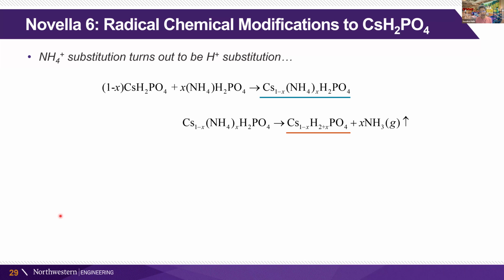What we discovered was that when we heated this material up to try to do the conductivity measurements and the thermal analysis, the ammonia, the NH3, evolved from the compound, and we were left with a material that was cesium deficient, and effectively proton doped. Now, we would have never tried to substitute cesium ions with protons because the size difference is so immense. Yet that's effectively what we created when we attempted to do ammonium ion doping.